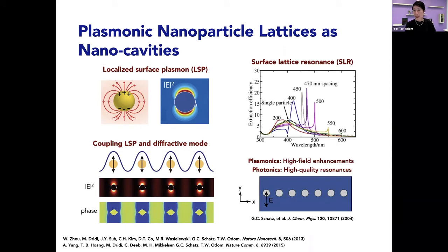And so what we gain is what we call these hybrid modes that have been commonly referred to in the literature as surface lattice resonances or lattice plasmons. And we take advantage of the photonic effects. So we are able to achieve high quality resonances. You can see that, for example, this 470 nanometer spacing, the line shape starts to approach sub 5 nanometers. And then we also maintain these high local field enhancements. So we end up taking advantage of the best of both worlds.